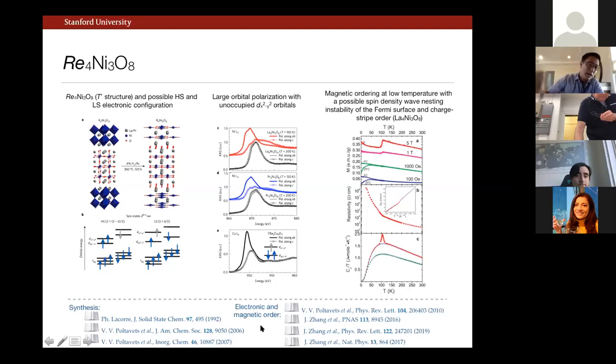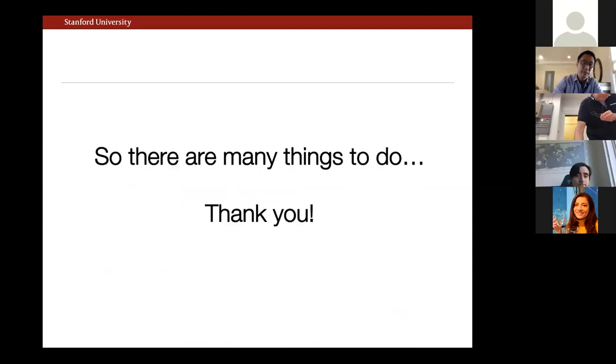So at least it's possible that the reason superconductivity hasn't been observed is that the chemical or the hole doping level is too high. I don't know if it's feasible, but one could imagine asking whether you can then do further chemical substitution on the rare earth site in order to explore the doping phase diagram of these, say, bilayer and tri-layer infinite layer polymorphs as well. So just a question and a speculation, but certainly an exciting one to think about going forward.